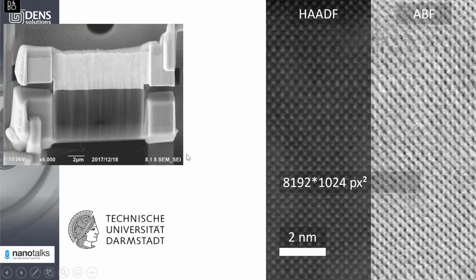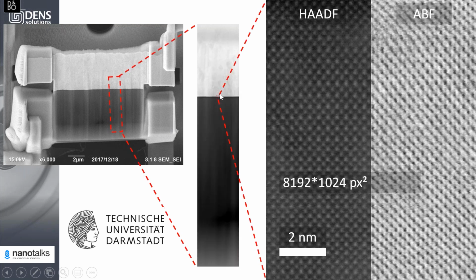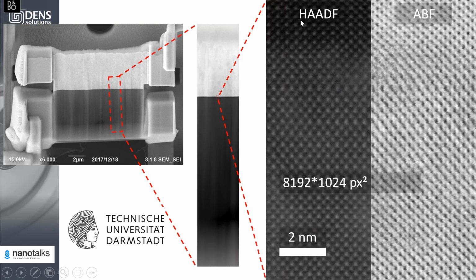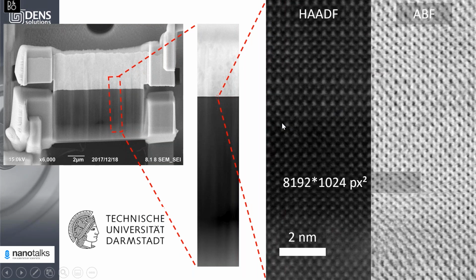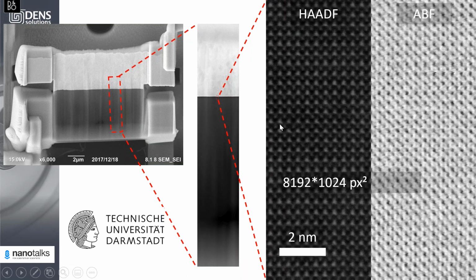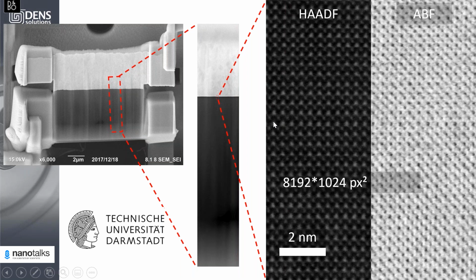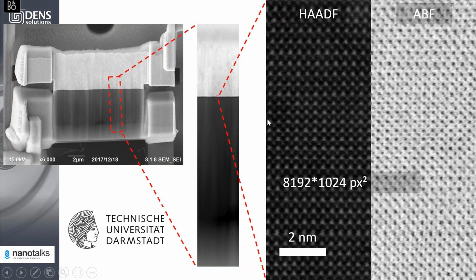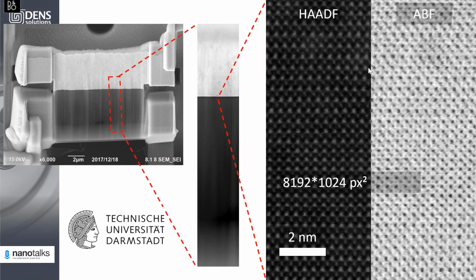And this is just one example to show you the lamella quality you can achieve using this approach. So this lamella was prepared at Technical University Darmstadt by Alexander Zindler and Leopoldo Molina Luna. So this is a lamella prepared on the nanochip. If you zoom in on this interface and then zoom in further, you can see STEM HAADF and ABF images, many images taken across the interface, stitched together. So with some practice, this is the quality you can achieve. And most importantly, having the means and the procedure to prepare samples allows the user to focus specifically on the experiment and not on solving issues with the sample preparation.